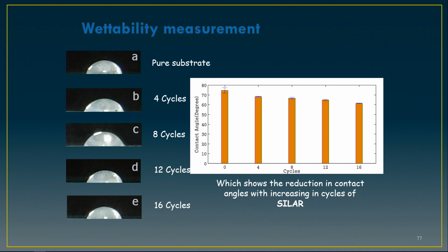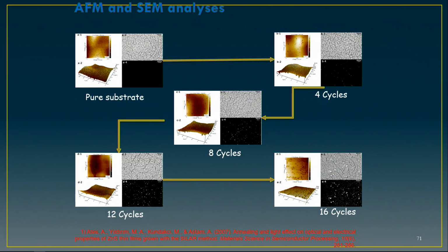We can change the contact angle. We can engineer the contact angle of the surfaces by different cycles of this method. And we also have other techniques by which we can change it. For example, by thermal annealing, by adding dopants, we can change the contact angle of the nanomaterials.